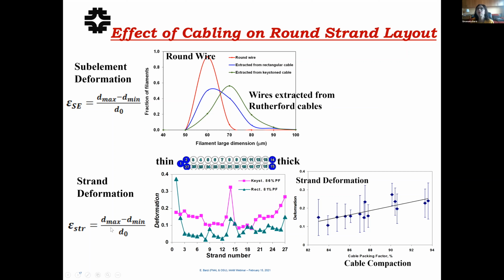Or we came up with a definition of deformation of the wire itself in the cable, not of the single little filament in the wire, but of the wire itself. And of course, this is the Rutherford cable. On the x-axis, you can see the strand location according to this legend. And of course, you can see the largest deformation of the strands at the two edges of the cable, as expected. And also, the average deformation of the wire itself increases with how much you compact the cable.